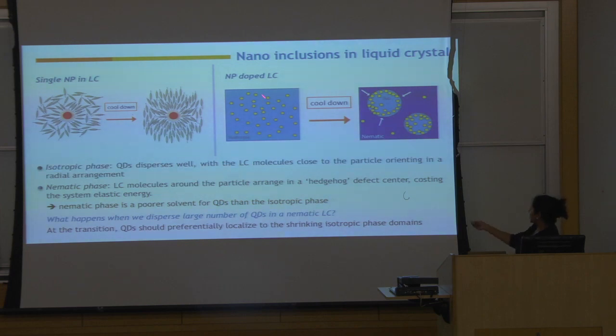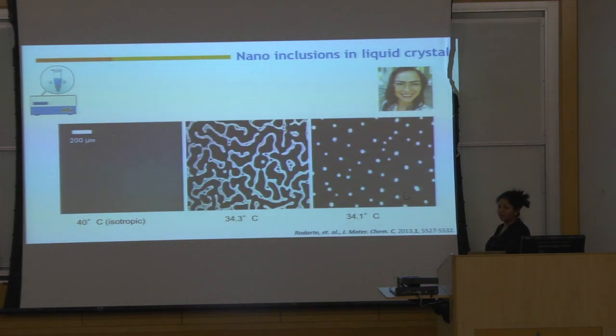So that's what happens when we put nanoparticles in here and cool it down. The nanoparticles, our first experiment we did was with quantum dots, are expelled from the ordered phase into the disordered phase. And this is what the experimental data looks like. This work was done by Andrea Rodarte. That's her picture there. You're looking at the fluorescence from quantum dots in liquid crystal molecules.